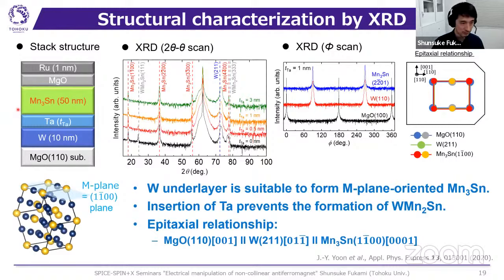Making a long story short, we found that tungsten is a very promising material due to the small lattice mismatch with Mn3Sn. But if we simply use a tungsten underlayer without tantalum, we observed unfavorable peaks, which indicate the formation of tungsten-manganese-2-tin. So this is unfavorable. So we inserted tantalum, and by increasing the thickness of the tantalum to thicker than 1 nanometer, this alloy peak disappears, and we just observed the favorable Mn3Sn peak. By the way, this Mn3Sn peak indicates the presence of the D0_19 ordered phase.